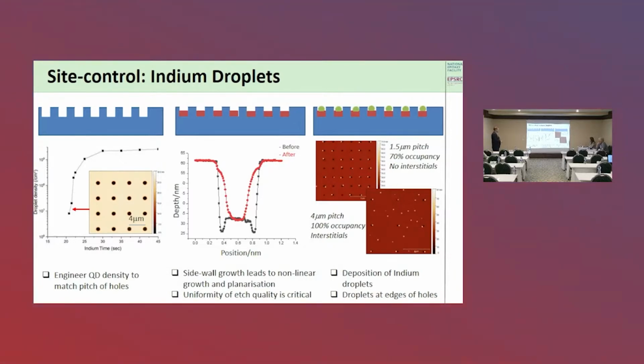Now the precise details of the pattern depends on what we want to do, and in fact for a pattern like this where they're 4 microns apart, the reason we want to do that is because we want to do optical excitation on a single dot, and our excitation spot is about that size. But if we were going to full circuits, we would obviously make much more dense structures, and then we match the density of the dots to that.